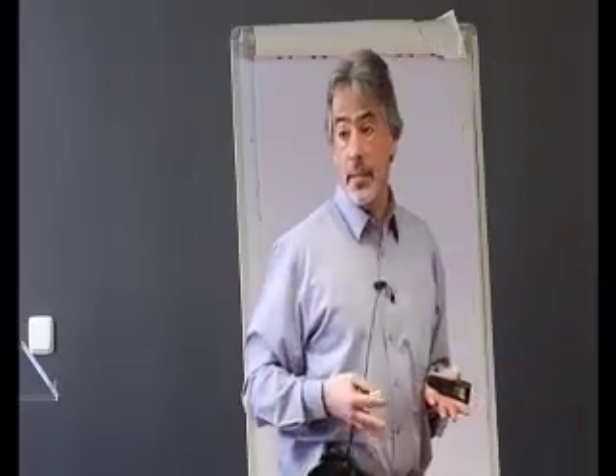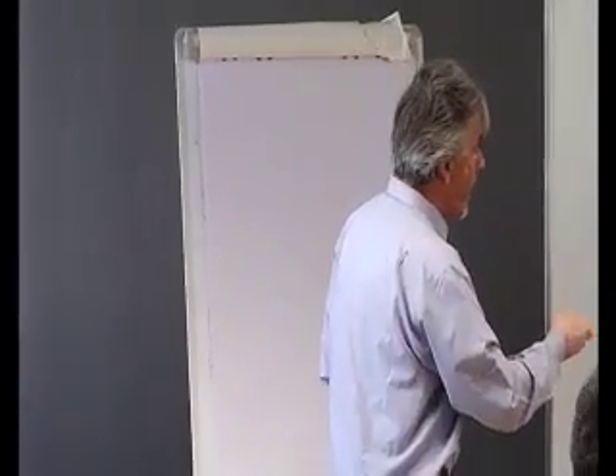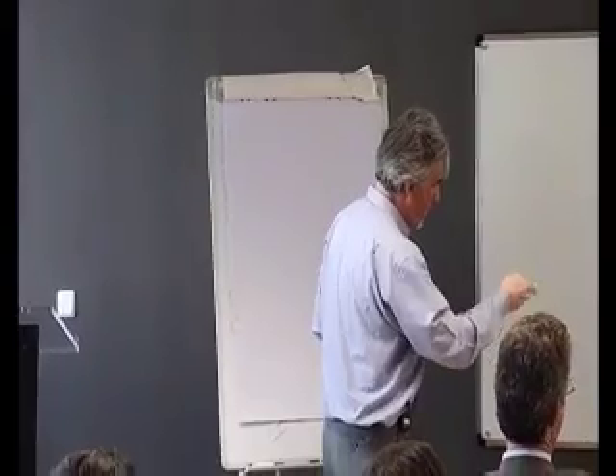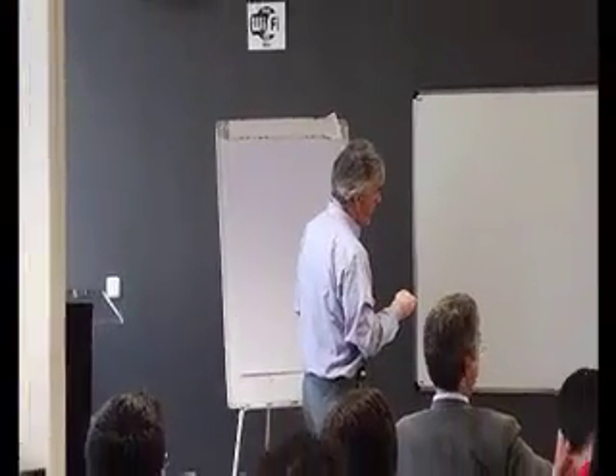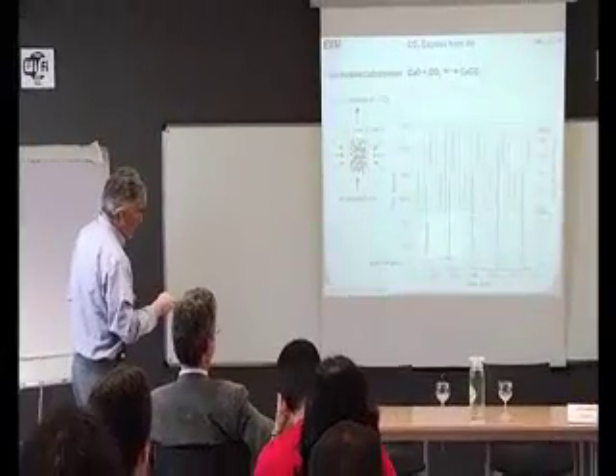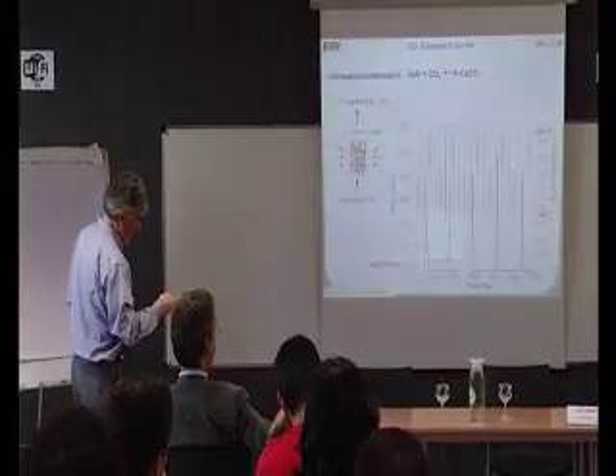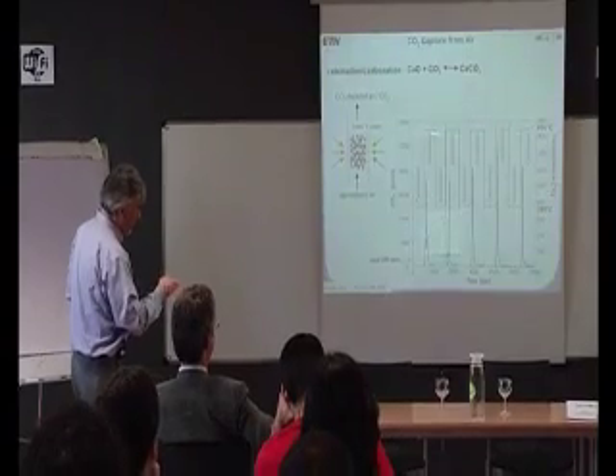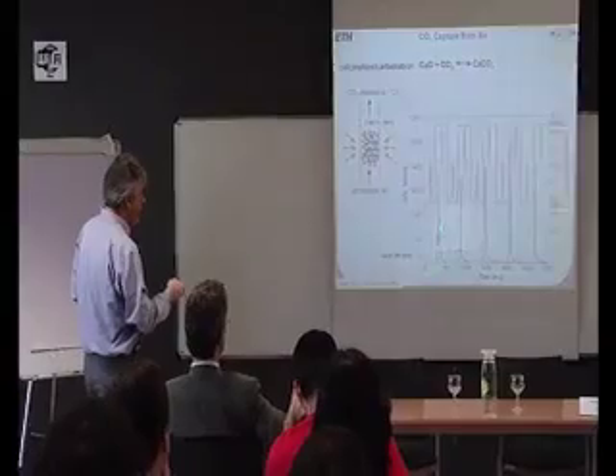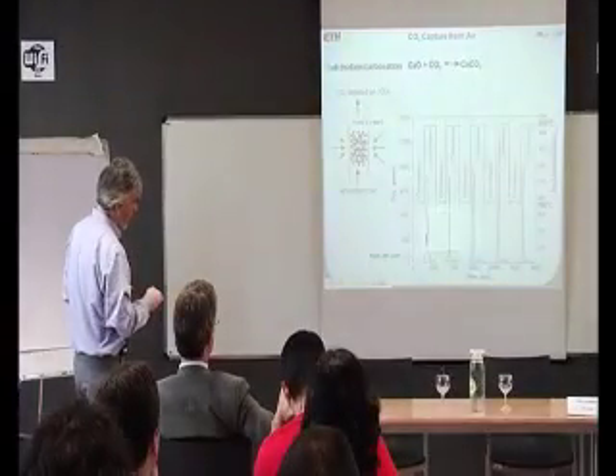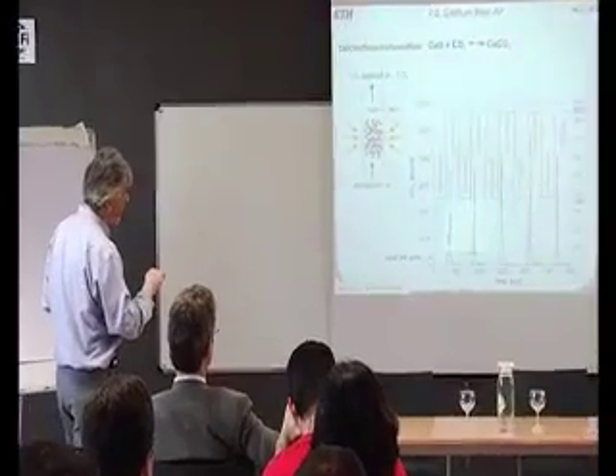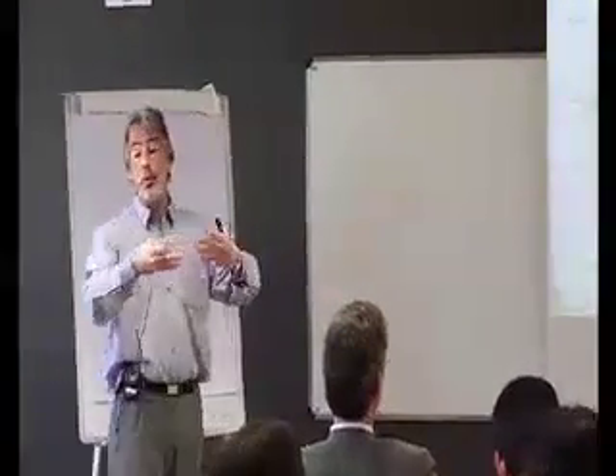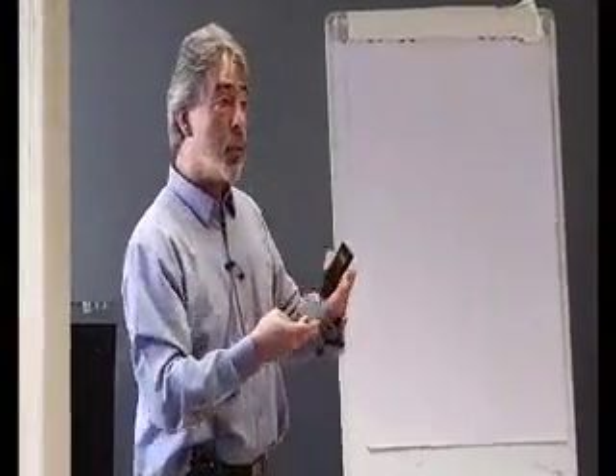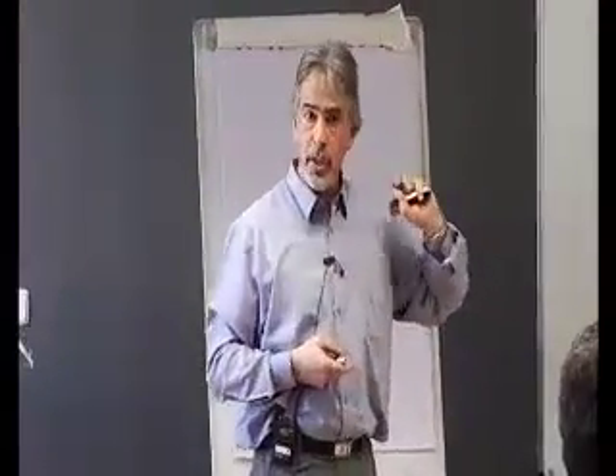This is an example of an experimental run in the lab where we ran 5 cycles. What you see here, first of all, the red curve, this is the temperature on the right side in degrees Celsius. So we are running carbonation at about 400 degrees Celsius, 390 degrees Celsius, and the calcination at about 850 degrees Celsius. And then the blue curve, measured on the left axis, is the concentration of CO2 at the exit. The way we measure, we are using an infrared detector with an accuracy of 1 ppm. We can measure the concentration of CO2.